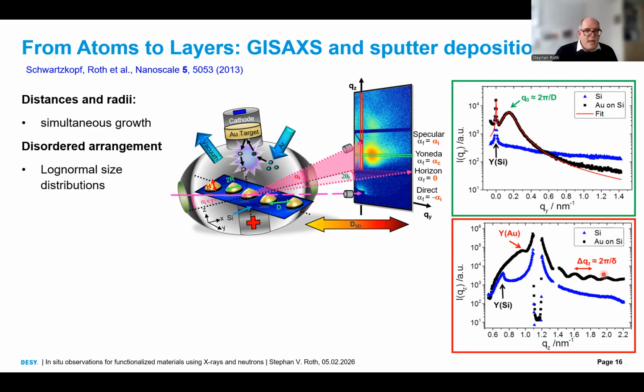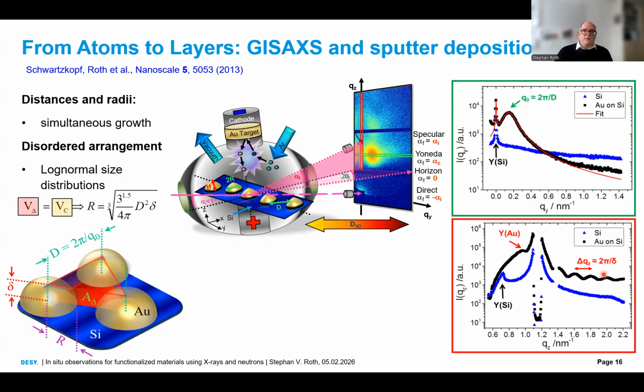And we have developed what we call a geometrical model. We know during sputter deposition, clusters occur on the surface. The distance of the clusters, d, gives rise to this peak here. When we now know how much material is on, this delta, and assume a hemispherical cluster shape, we can calculate the radius of our nanoparticles only by the position of this peak and by knowing how much material is on. And this allows us during the deposition to follow the nanostructural growth of the cluster.